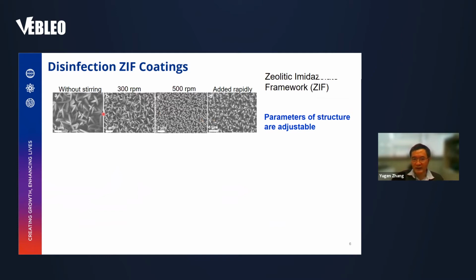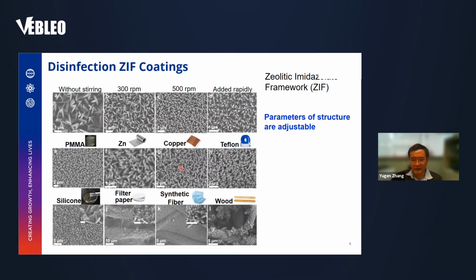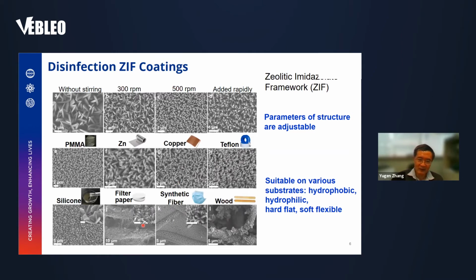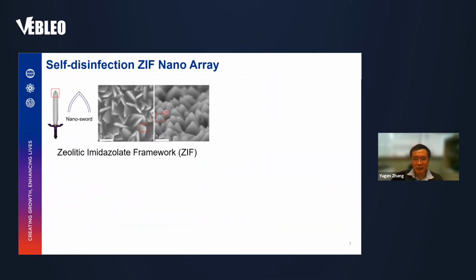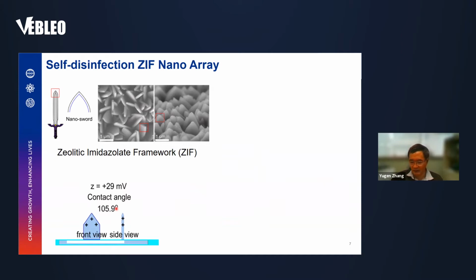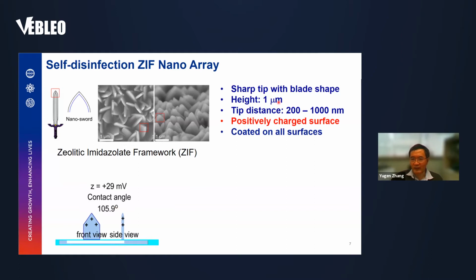Firstly, we can glue this nanostructure on different surfaces. We can control the parameters of the structure by simply adjusting the synthesis conditions, as shown here. And we can glue this nanostructure on various surfaces, from very hydrophobic ones like Teflon to hydrophilic ones like wood and filter paper. It can be easily glued on a hard and flat surface, and it can also be glued on a flexible surface like synthetic fiber. This is how it looks. We call this a nano sword or nano dagger, and it has sharp tips. It has a positive charge on the surface because we use imidazole as a ligand for these materials. The height is typically about 1 micron, and the tip distance is about 200 to 1,000 nanometers. So we can glue or coat this structure on various surfaces.